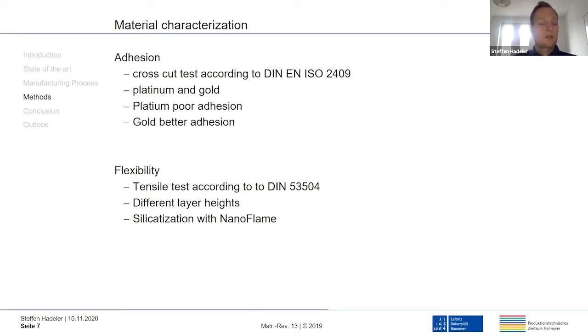The adhesion of these structures transferred from the transfer substrate of polyvinyl alcohol to the PDMS was tested in a cross-cut test according to the norm, and samples were prepared and evaluated with platinum and gold. In this test, the platinum coating was stripped from the PDMS much more easily than the gold film. Thus, gold has a higher adhesion to the PDMS after transfer from the PVA. This observation can be explained by the different surface energies of the materials, and the transfer process to the PDMS occurs with platinum with significantly more defects, since the adhesion to the transfer substrate is high.